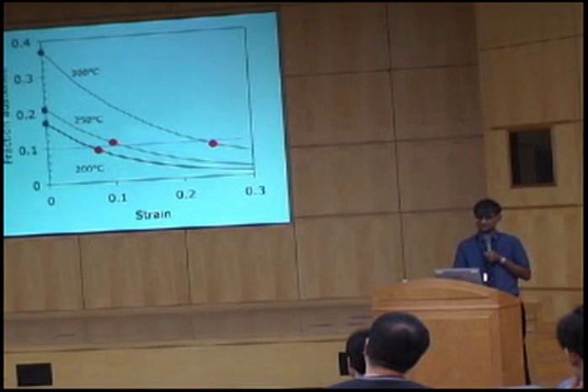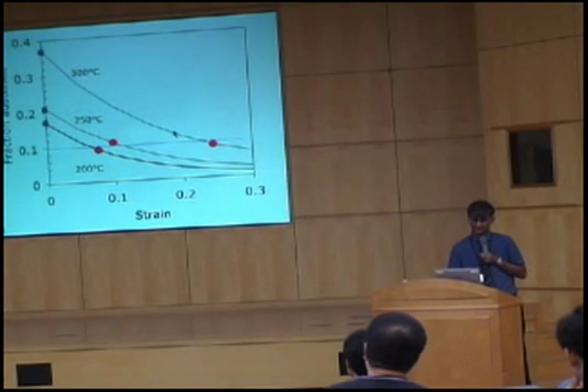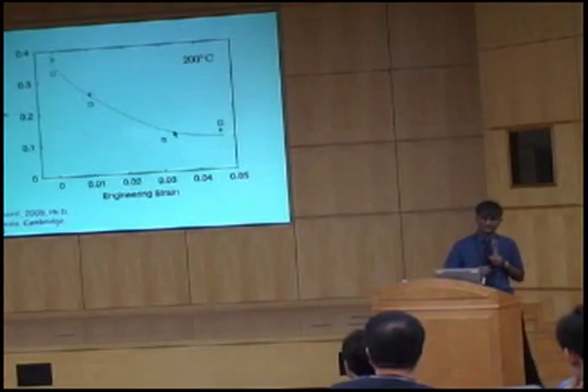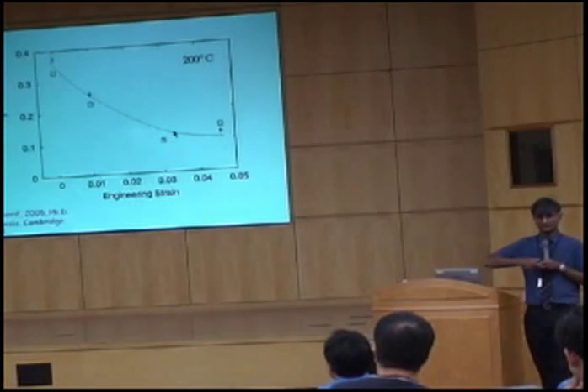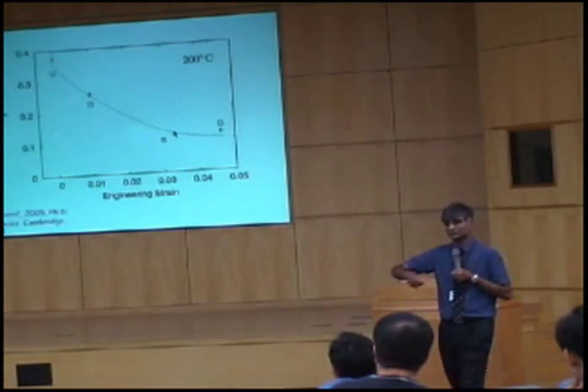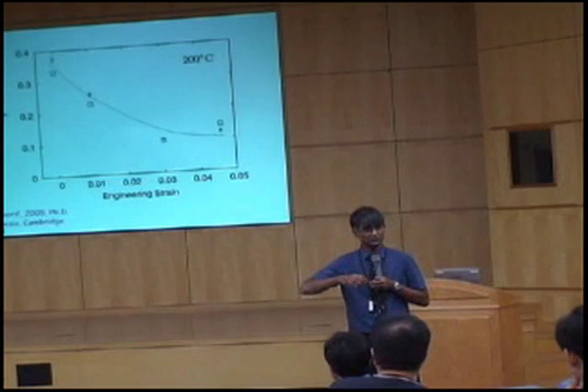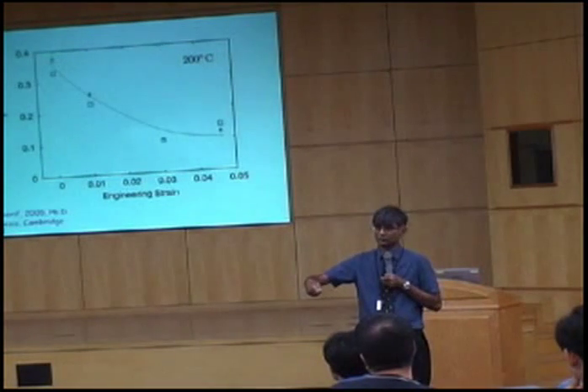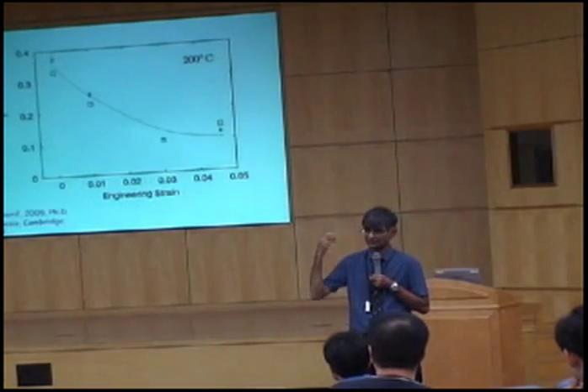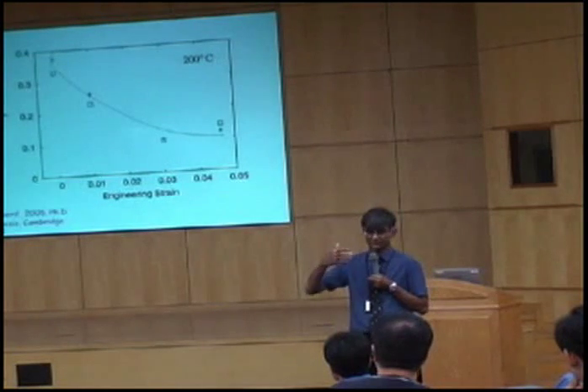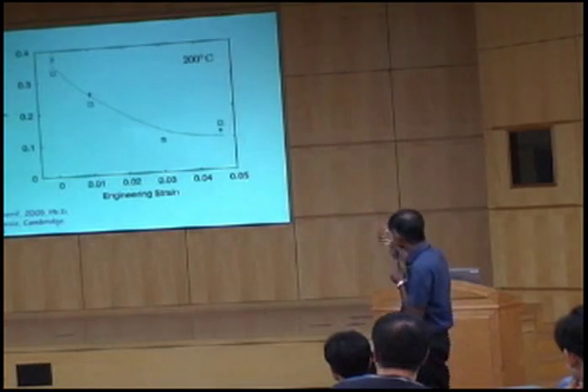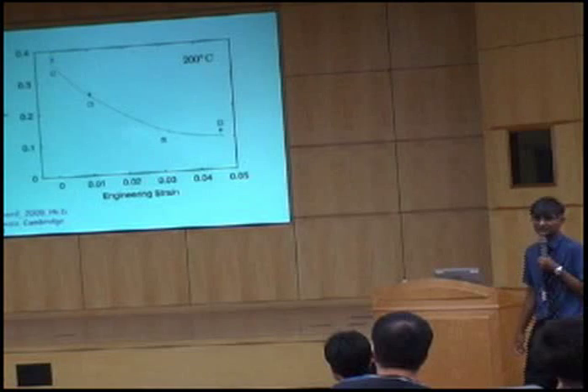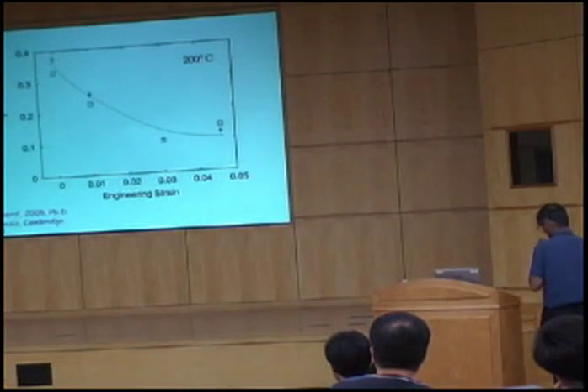Just to show you that these are actually calculated curves, but we did some measurements of a tensile test in an experiment where we monitor the fraction of austenite as it transforms using neutron diffraction. Okay, and the same result comes out that you get fracture when you reach about 10% of austenite remaining in the microstructure.